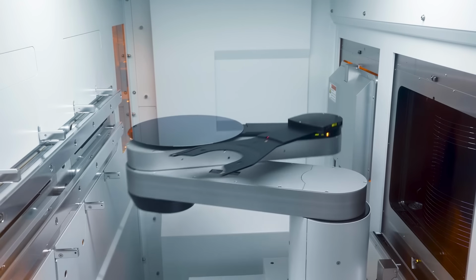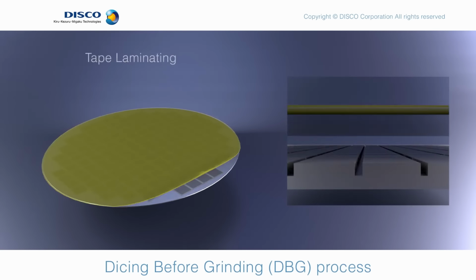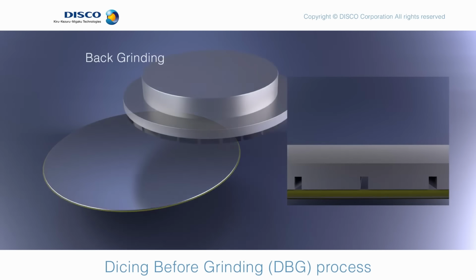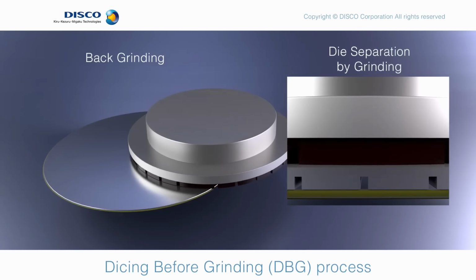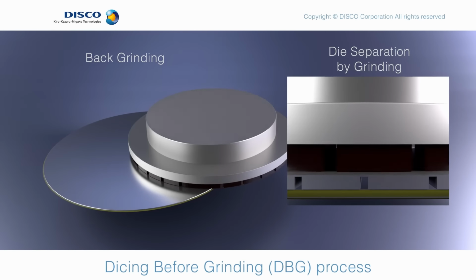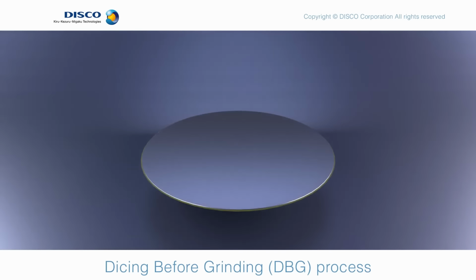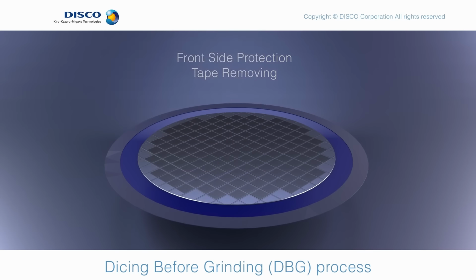But in order to stack a chip on top, which in the case of a flip chip means stacking it on the back, you have to remove the structural silicon on the backside. To allow the cache chiplet to connect, the CCD first has to be thinned down in a process called wafer thinning. An entire wafer of Zen 4 CCDs is thinned at the same time. The result is that only the super thin transistor and metal layers of the CCD remain. It's also a very delicate process, because wafer thinning impairs the structural integrity of the original wafer by removing the silicon that was providing the structural support in the first place. For that reason, so-called support or carrier wafers are used during the process, which are bonded to the wafers that are being thinned down, so they don't collapse when they become too thin.